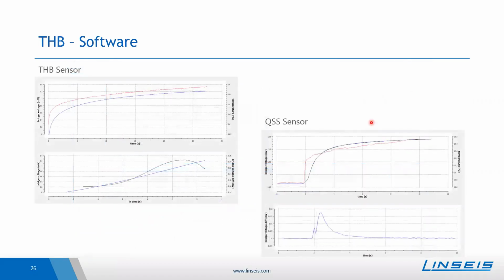So depending on the type of the sensor, the recorded measurement curve looks a little bit different. For the THB sensor, you can see an example here. We record the bridge voltage and also the temperature increase. And from the bridge voltage, we need to take the derivative for the THB sensor to be able to determine thermal conductivity. For the thermal conductivity, here the maximum is relevant, and for the thermal diffusivity, here the decrease. So the shape should be similar to this black curve.